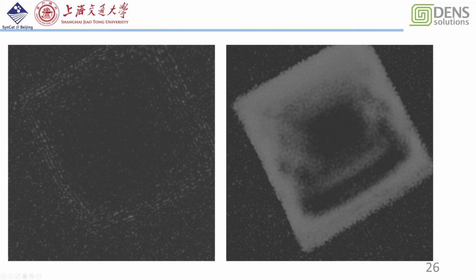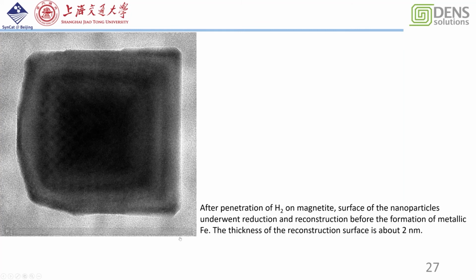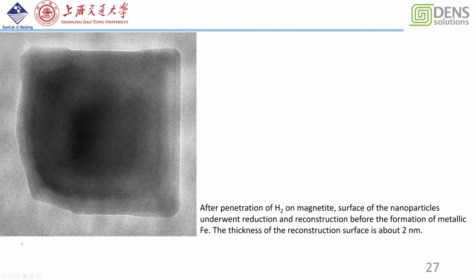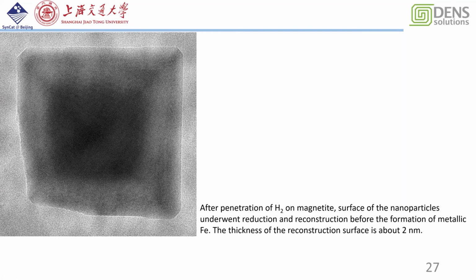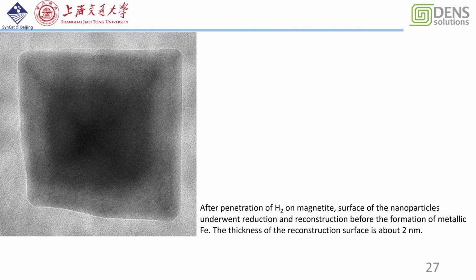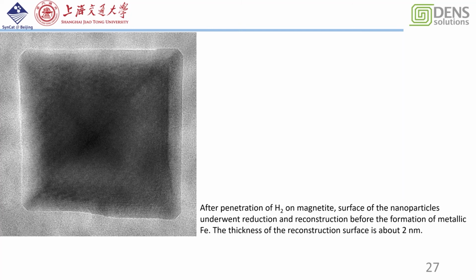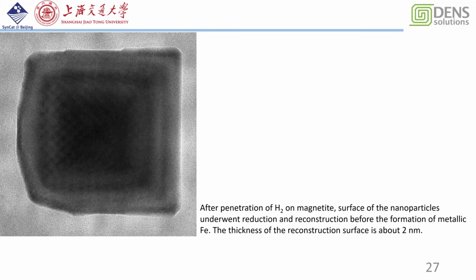And we found this happens generally for all kinds of iron oxide nanoparticles. Because this is an overlapping problem with the surface reconstruction, if the magnetite doesn't have a very good shape, or is not in the right orientation, we cannot see it at all. But if we can get this octahedral particle in the right direction, we can see the same reconstruction process on the surface. And this suggests that the new species forms and covers the surface, and afterwards is removed by the reduction process.